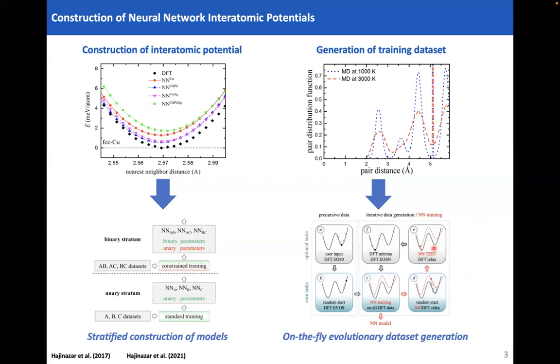These are just default values, which we found suitable for the applications that we were interested in. So you do the search again, and at each stage, the code looks through all the structures which are generated, finds the unique ones, and submits them for DFT calculations. And based on the discrepancy of the DFT energy and the energy calculated by the machine learning, it estimates how bad the machine learning model is, or how good it is on the other hand.